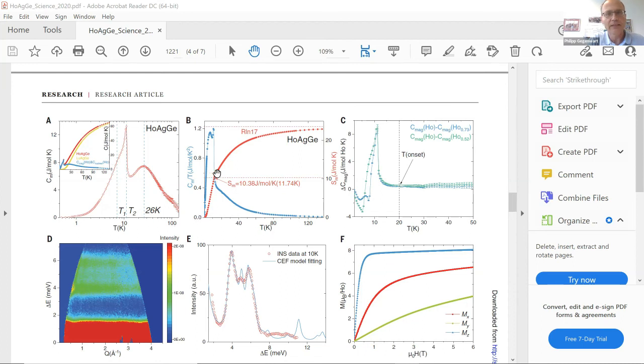And we calculated the entropy, and of course, there is some uncertainty due to the phonon subtraction, but it doesn't seem that a substantial fraction, at least on this scale, which is enormous, R ln 17, that a large amount of entropy is missing. I mean, one has to keep in mind, these are large spin orbit coupled moments. We have the crystal field splitting,